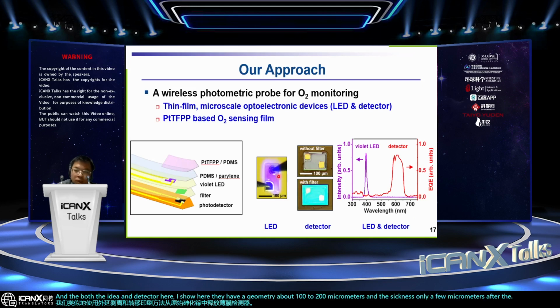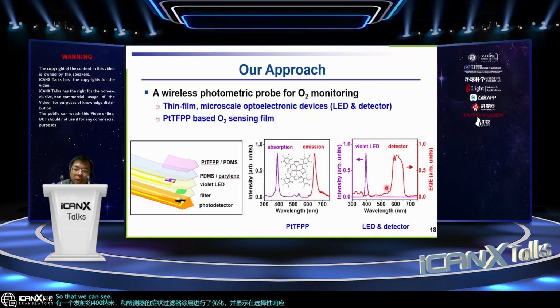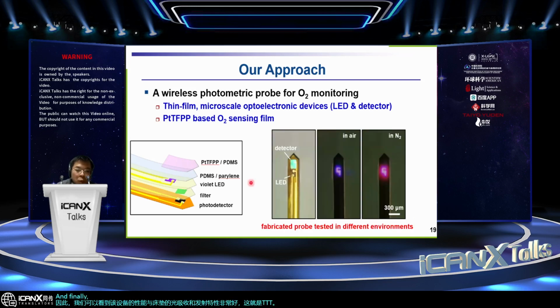The violet LED has an emission around 400 nanometers, and the detector is optimized with a thin film filter coating and shows a selective response in the red region, so that the device performance matches very well with the optical absorption and the emission properties of this PtTFPP molecule. And finally, all these components can be heterogeneously integrated on a thin film flexible substrate, and the probe structure is formed by laser milling. Because of the coating on the probe surface, we can see a very bright red emission color when the oxygen level is reduced.